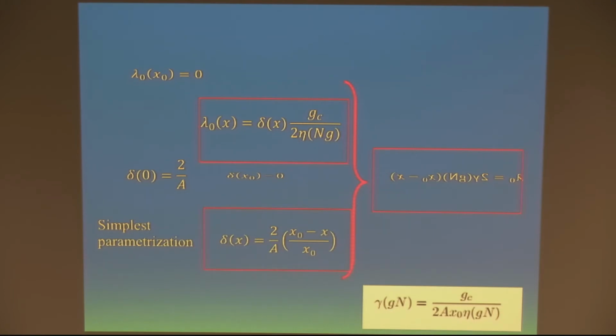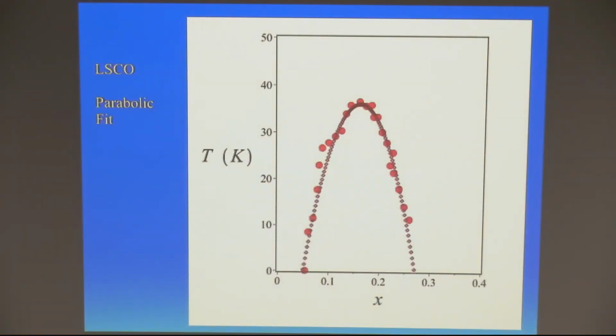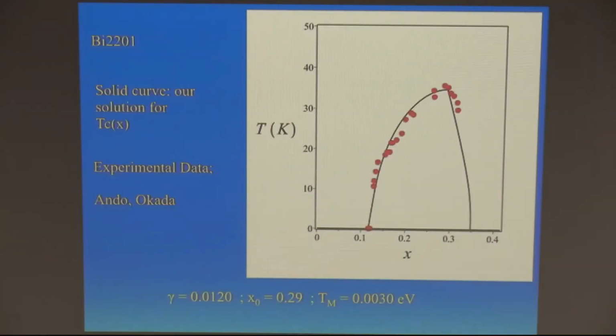Okay, you see this delta is a function of the area of the primitive unit cell. So this area is certainly a function of the pressure. So if you apply pressure, this area will diminish, decrease. So it's very easy to study pressure effects in this framework.